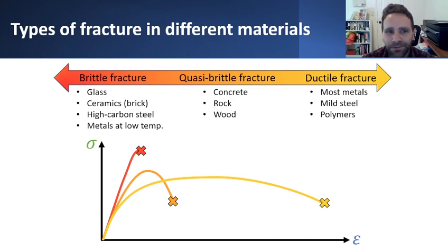But again, it's important to emphasize that the mechanisms governing fracture in these different types of materials on this spectrum of brittle to ductile fracture are quite different, and it's really not appropriate to apply certain concepts of fracture mechanics to all of these different classifications of materials. You have to specialize your discussion of brittle fracture and fracture mechanics geared more towards the brittle fracture domain, which is really only where classical linear elastic fracture mechanics applies. It doesn't apply so well in the case of ductile fracture. For that, you need a little bit of a different approach. So just bear in mind that a lot of classical developments in fracture mechanics are geared more towards the left end of this spectrum, towards brittle fracture. But we can still get away with applying them in certain contexts.